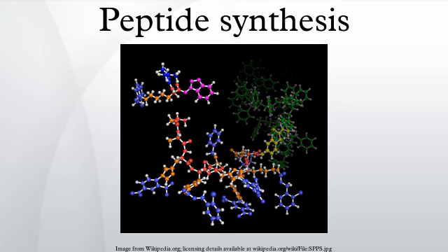There are four primary types of solid supports. Gel-type supports are highly solvated polymers with an equal distribution of functional groups. This type of support is the most common, and includes polystyrene cross-linked with 1–2% divinylbenzene; polyacrylamide, a hydrophilic alternative to polystyrene; polyethylene glycol, PEG-polystyrene, which is more stable than polystyrene and spaces the site of synthesis from the polymer backbone; and PEG-based supports, composed of a PEG-polypropylene glycol network or PEG with polyamide or polystyrene.